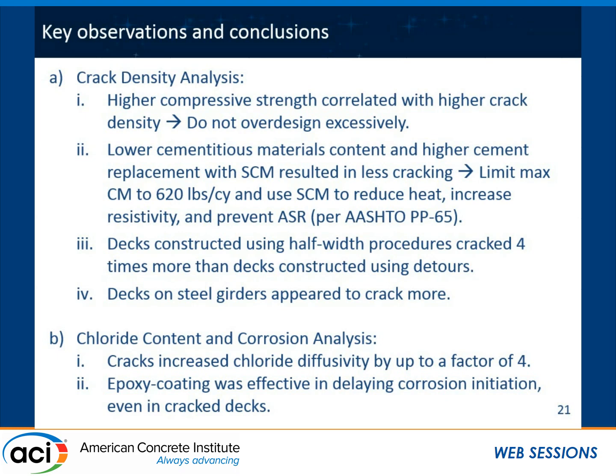Have you done any analysis on those crack widths and found any correlation between the width and the diffusion coefficient or the concentration of the chlorides? Because there are two different ideas about the effect of cracking. Some people say that regardless of the size, cracking will increase the rate of chloride diffusion or the concentration of the chlorides at the rebar. Or the other side says that there is a threshold value, that only cracks larger than a threshold value will affect this. And if the crack width is below that threshold value, it doesn't affect the diffusion that much. So I'm just wondering if you have done any analysis of those.